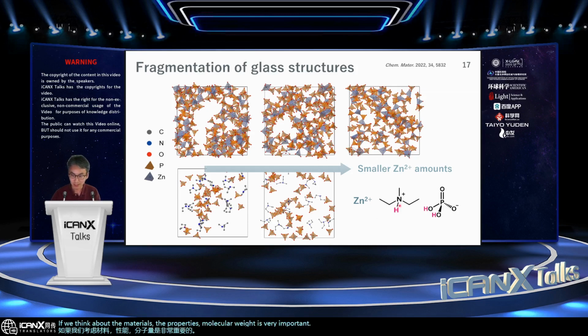So in this case, we have done the reaction with zinc and this protic ionic liquid. But if we reduce the amount of zinc ion used, as expected, this networked glass structure fragmentation occurs like this. Which means this networked glass domain is going to be very small, and which may contribute to the differentiation of the proton conducting properties.